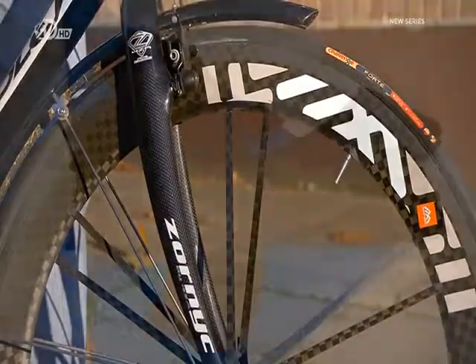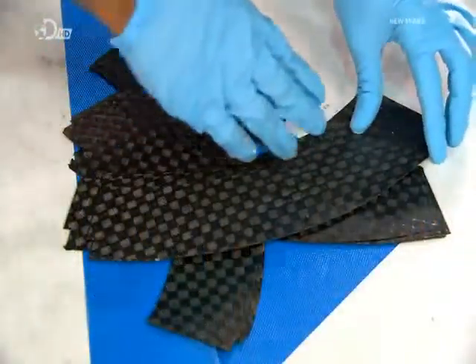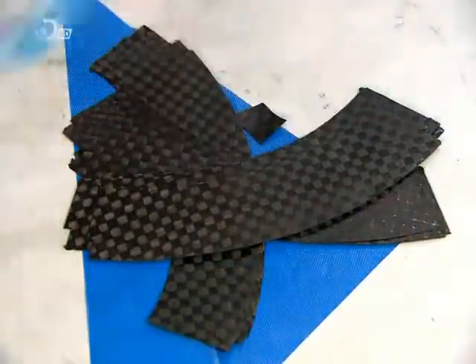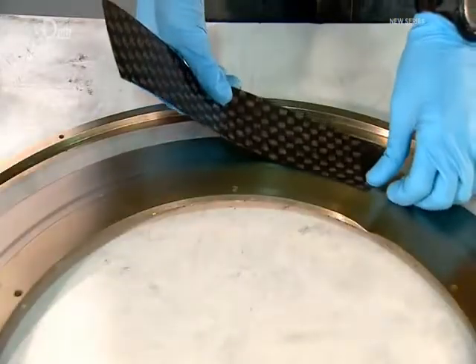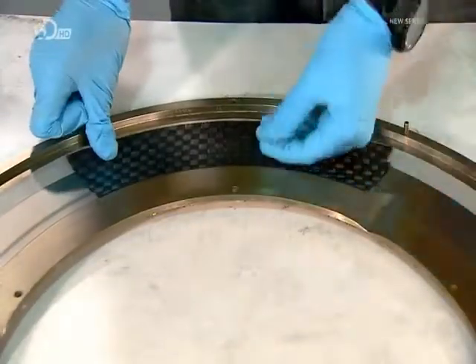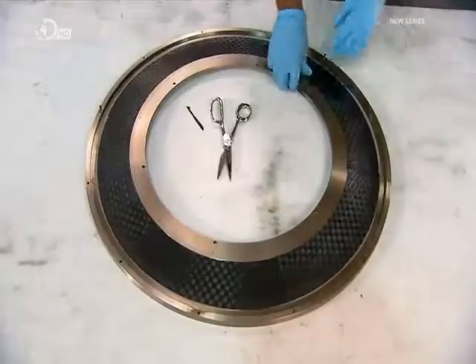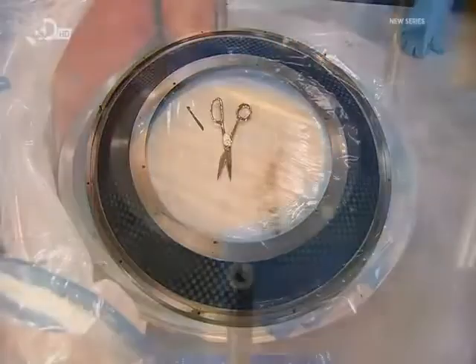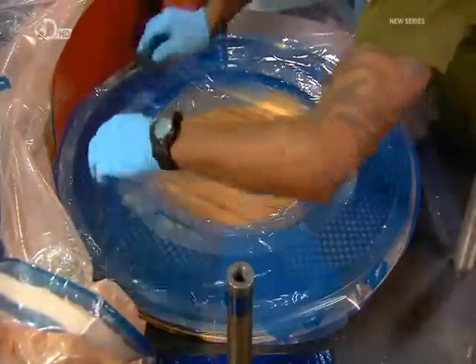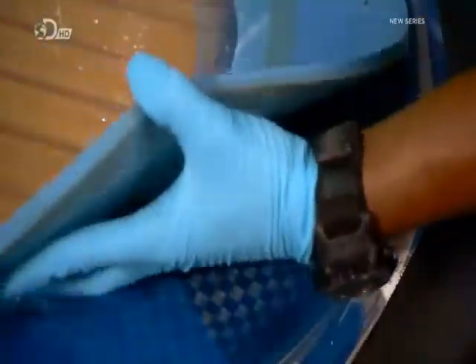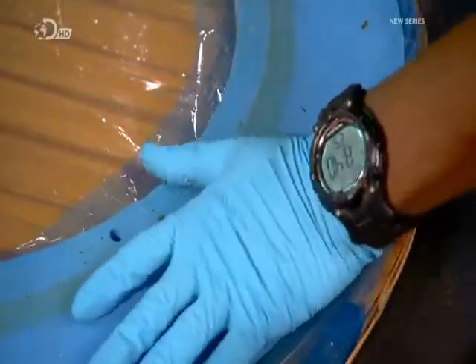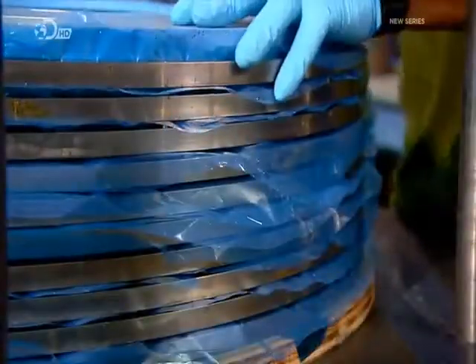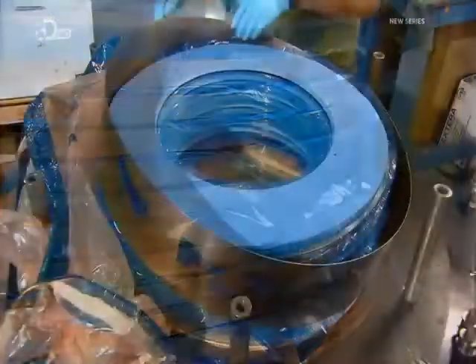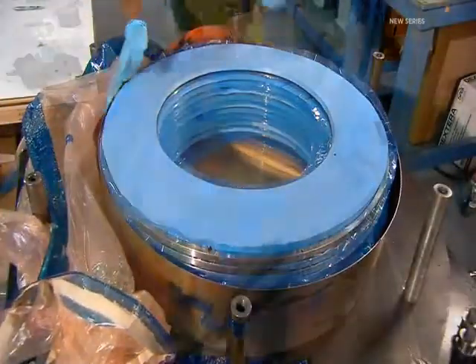They start by cutting carbon fibre into patterns, and these arcs are for half of a sidewall. The technician layers them onto a band of fiberglass in a mould. The fiberglass will provide a good surface for braking. He drapes a piece of non-stick plastic film over the mould and adds a silicone pressure pad. He stacks several moulds, each with a silicone pad and plastic film.